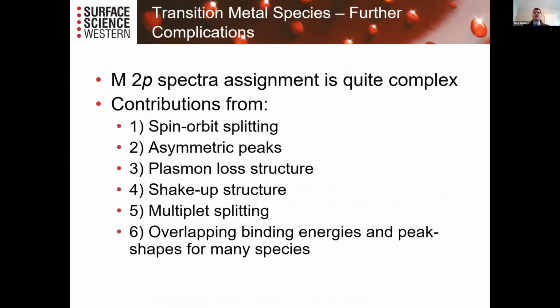When you get into the transition metals, things start getting a whole bunch more complex. You have contributions from spin orbit splitting. You can have asymmetric peak shapes, loss structure, shakeup structure, and then the big one is multiplet splitting. And for all of these materials, you can get overlapping binding energies and varying peak shapes for many different species. So what do I mean by that?